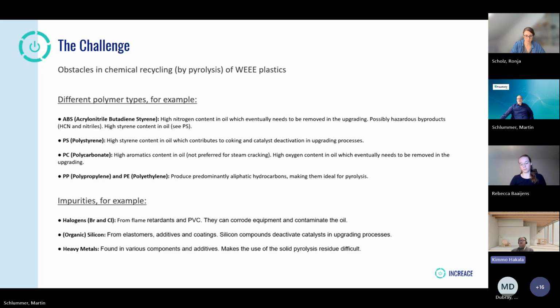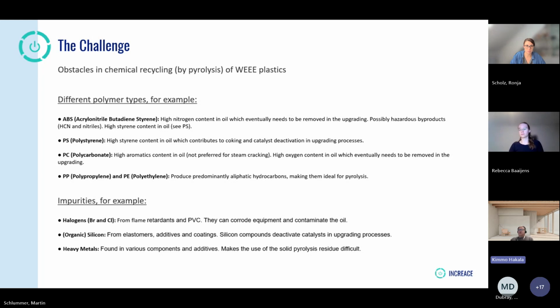So the target here is the chemical recycling of these WEEE plastics, and I start with the challenge. The challenge is that there are many different polymer types, and of course you can pyrolyze different types, but then if you target the steam cracker, like here in our model, we see it on the next page. There are certain plastics which fit better to that pyrolysis approach, and certain which do not. So ABS is not very suitable. You get, of course, acrylonitrile and styrene there and some secondary products from those. If you pyrolyze polystyrene, you get a lot of styrene, which is also not good for the upgrading, and you should not have it when you feed to the steam cracker.